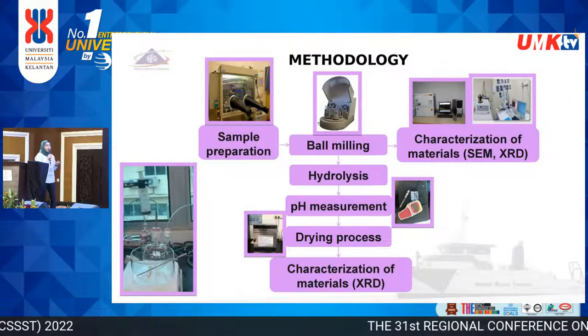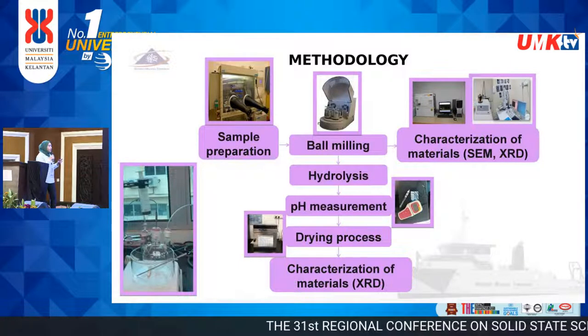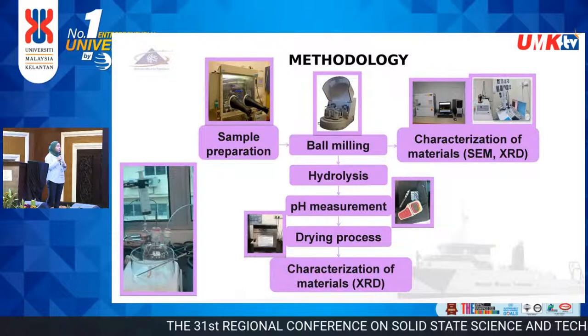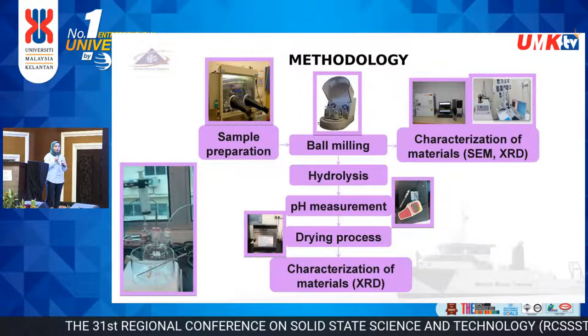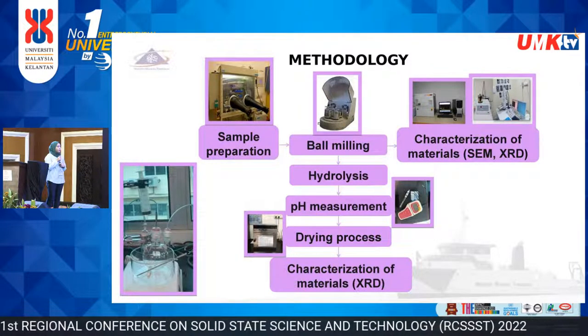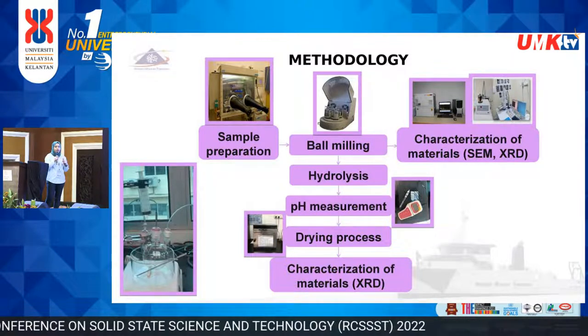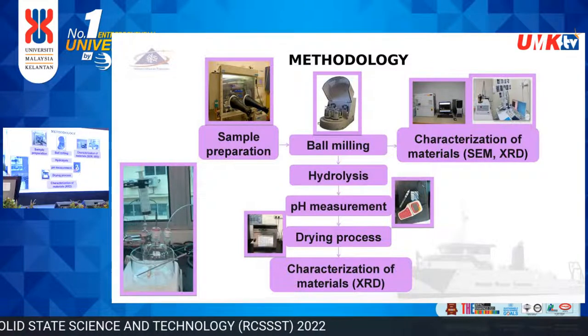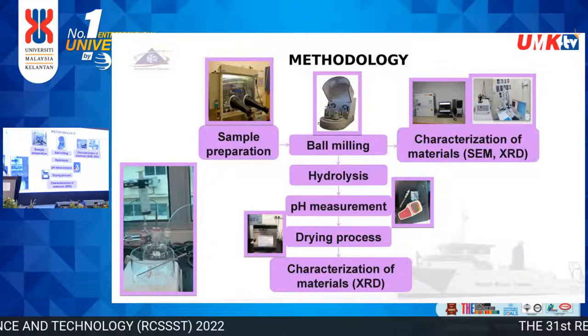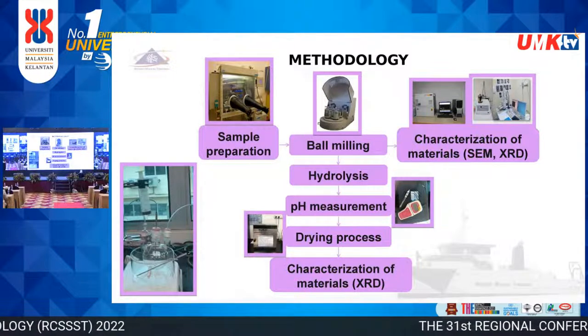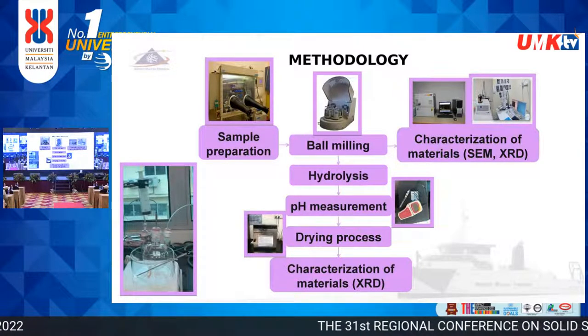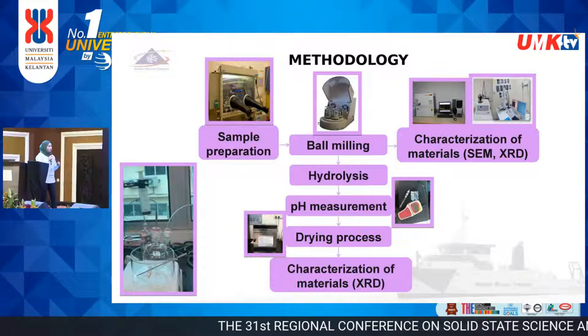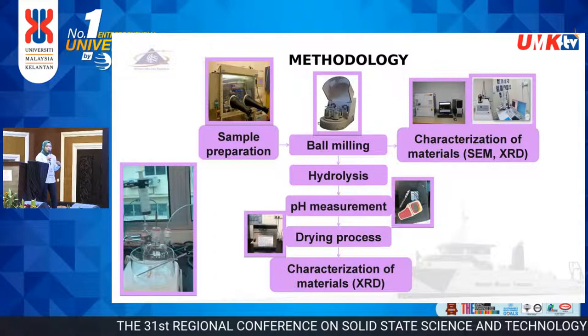So this is the methodology. All the sample preparation will be done in a glove box. This is to avoid contact with air and moisture. Ball milling will be conducted for 1 hour, and after that, the hydrolysis process. After hydrolysis, the pH reading will be taken and the samples will be filtered and dried to undergo characterization by using XRD.